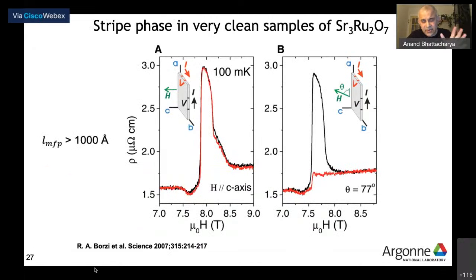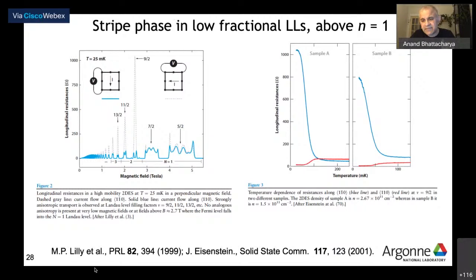This story is not new in the context of stripes. It was actually found also in strontium ruthenate. I'm not going to go into the details of this experiment, but in essence, when they made their sample very, very clean, there were like three Science papers over several years, and when they got their samples really clean, to about 1,000 angstroms mean free path, that's when they began to really see this nematic phase. Also very famously, in the 9½ filling factor two-dimensional electron gas in these low Landau levels, Eisenstein and his co-workers found that there was a nematic phase that developed in their sample: a lot of resistance anisotropy, depending on which way you flowed the currents in your sample.